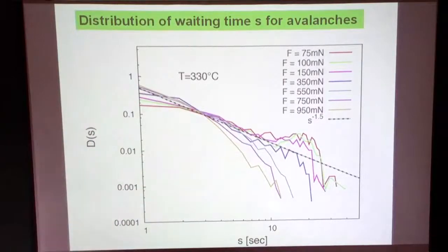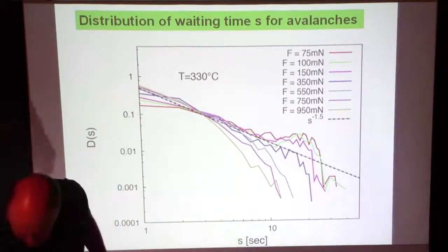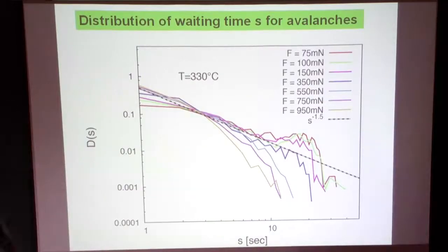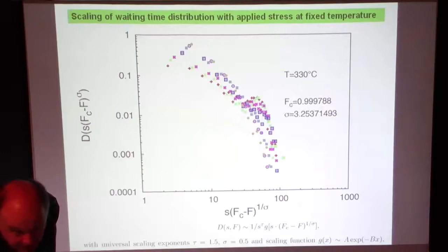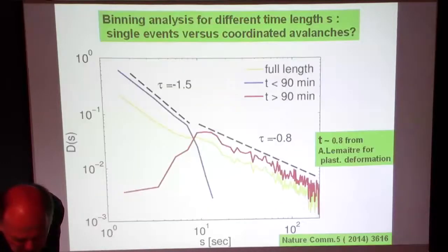Karin has spent a lot of time trying to figure out what the distribution could look like if you're at different levels of stress. And then it's a very strange loading mode that you're in, because you're putting it in creep near yield, but at different times during the creeping, yes, it's going to be behaving differently. In their case, right? Yes. And I'll show you where we really differ. You know the data, right? This is just for a certain time measurement, and that's fine. But when you're doing the statistics, you put on the load, and then throughout the duration of the creep, you take statistics for the whole duration of the creep. Yes, exactly. Well, you have it on half a decade, more or less. Yeah, it's only limited. But what now?